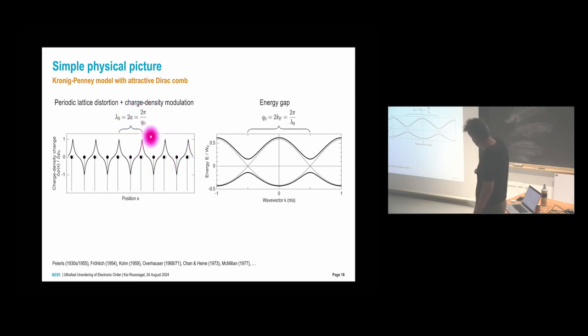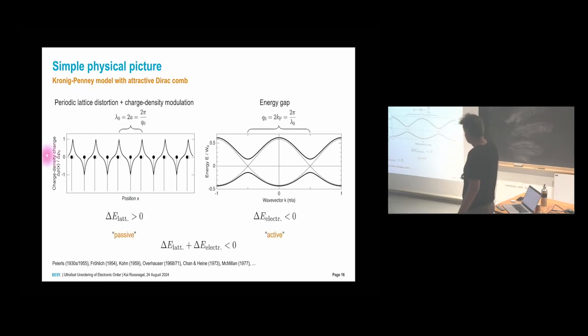Yeah, and this Q vector, which corresponds to this wavelength, you find in energy wave vector space, and this is this vector here, which connects your two Fermi points. Yeah, and if you have this modulation, then this can give rise to the opening of this energy gap, and this energy lowering of your electronic states here stabilizes the energy cost of moving atoms and bringing charge closer together in real space. Okay, so these are the passive terms. You have to move atoms from the equilibrium position. You have to act against Coulomb repulsion to bring electrons together. And this is the active term, which gives you this energy lowering. And if the total energy is below zero, you have stabilized this state.